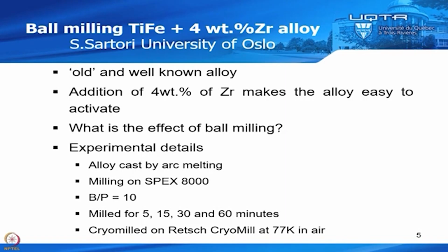So we cast the alloy by arc melting, and then we mill it on a SPEX machine, a high energy milling machine. And we mill for 5, 15, 30, and 60 minutes. And also we tried cryo milling, so milling at low temperature, but this time it was in air. All the other milling here was done in argon, but the milling at low temperature was done in air. And we will see that this made some problem.